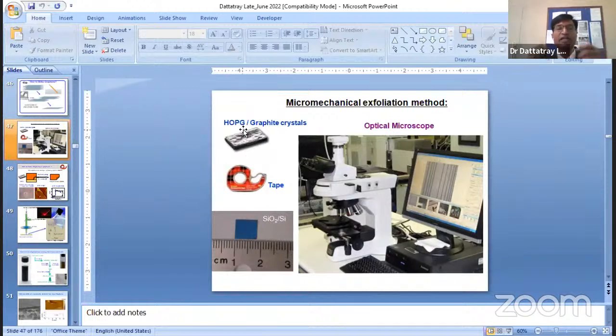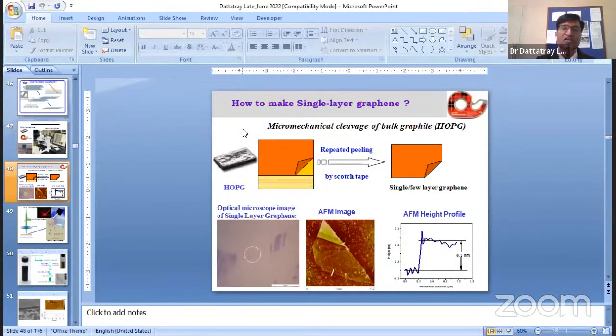What you need to do, you have to take this tape and put the tape onto this HOPG crystal. You put slight pressure, you take out that tape, and you put it on the SiO2/Si substrate. You put small pressure again on the tape, and you take out the tape. You can go to the optical microscope and see what color contrasts you are able to see.